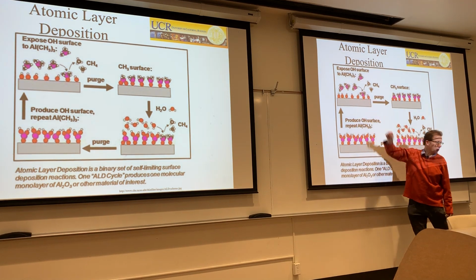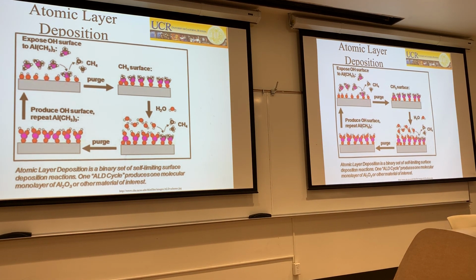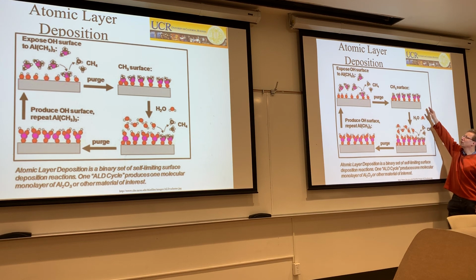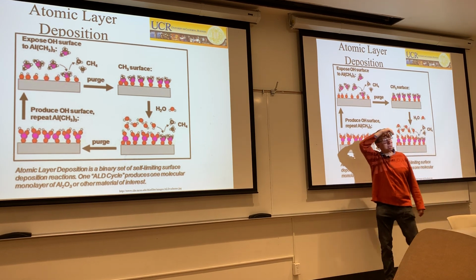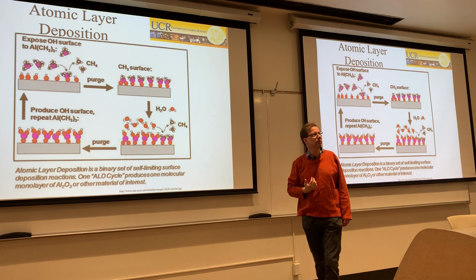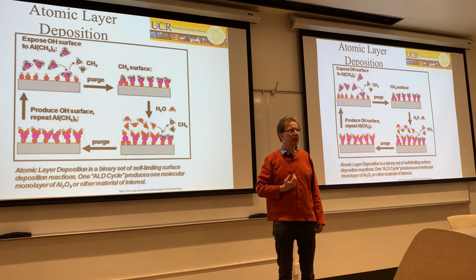I come with a metal organic aluminum compound, which is in a gas phase, which I evaporate. When that comes on the surface, one of the methyl groups exchanges with the hydrogen from the hydroxyl, and the aluminum sticks to the surface, still having methyl groups exposed, one or two on top of it. And this process will end if the whole surface is covered with this methyl aluminum species. Then you have exactly one layer.